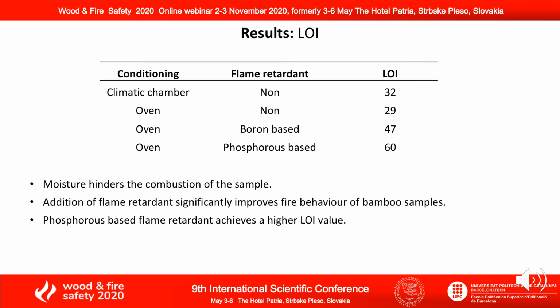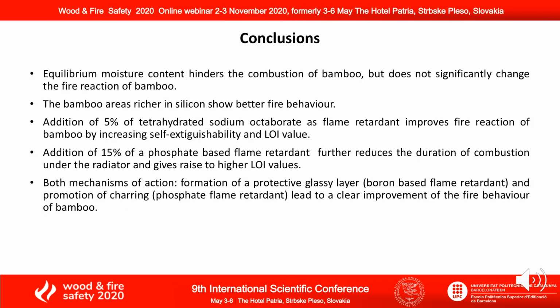In the limiting oxygen test, we observe that the moisture hinders the combustion of the samples by increasing the oxygen index value, and that both flame retardants can improve the fire behavior of bamboo samples by significantly increasing the oxygen needed to sustain the combustion of these samples. In the case of the phosphorus-based, this effect is higher than for boron-based flame retardant at the concentrations tested.